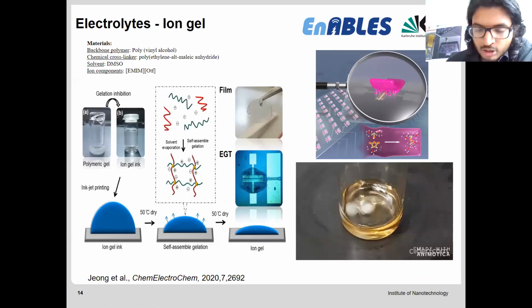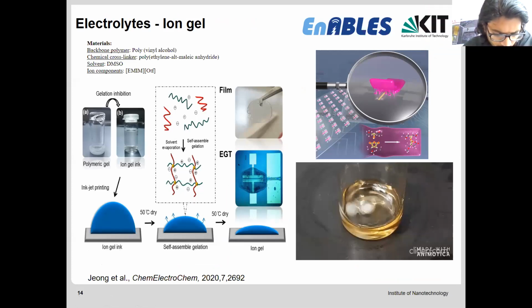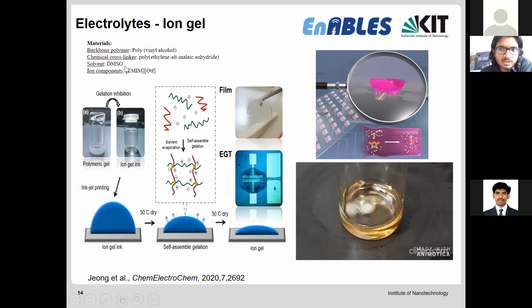In order to make electrolytes, there are a variety of materials that can be used. In this case, I will show you one of the electrolytes that we use. This is called an ion gel, wherein we add a backbone polymer of PVA and also PEMA, and there is a solvent, DMSO, and this DMSO solvent keeps the overall electrolyte quite dilute so that it can be inkjet printed. And once the DMSO is evaporated, obviously once we put a solvent, the solvent has to evaporate, the PVA and PEMA cross-link physically because of the drying, and then they turn into a gel-like structure.